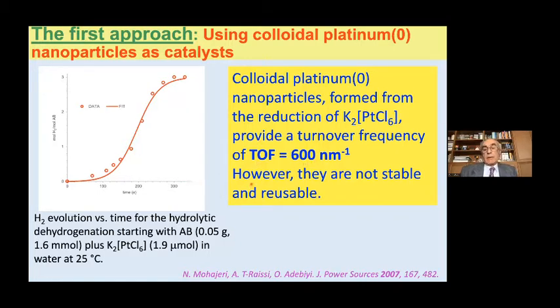Okay, however, they are not stable. These nanoparticles, colloidal nanoparticles, are not stable because there is no stabilizing agent in the system. Just the chloride anion, which is a very weak stabilizer for the platinum nanoparticles, and therefore they are not stable and therefore not reusable.